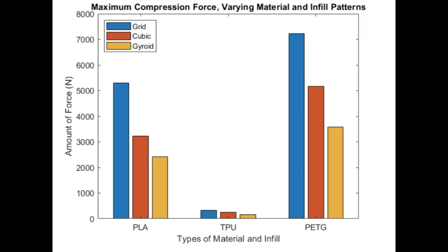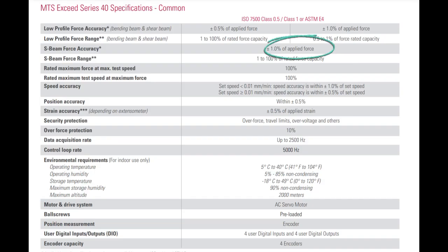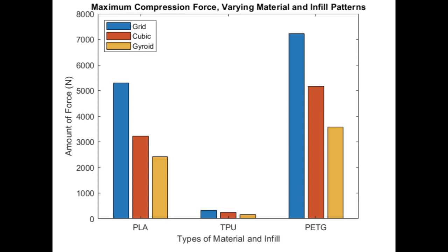Here we have the compressive stress results for each material and infill pattern. From the MTS Exceed manual, we could find that the force accuracy of the E43 machine is within 1% of the applied force. Comparing the maximum forces for the grid pattern, which was the strongest infill, the maximum force for the PET-G was about 7,200 newtons, followed by the PLA at around 5,300 newtons, and lastly, the maximum force for the TPU was only about 320 newtons.